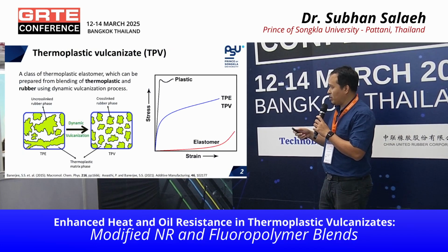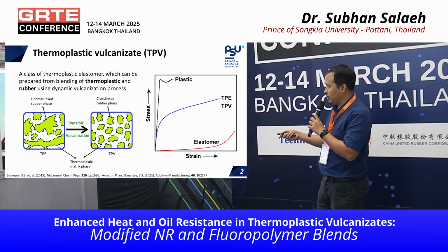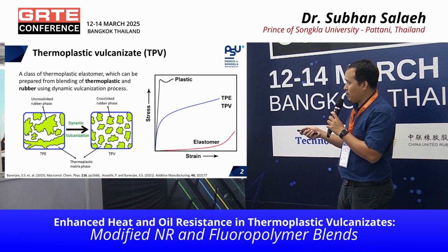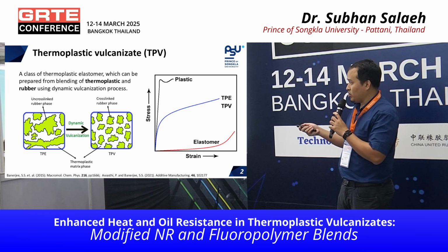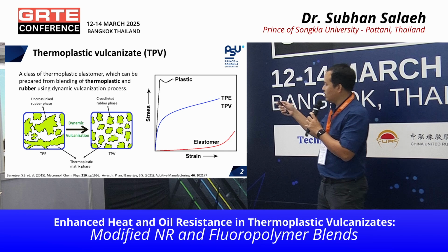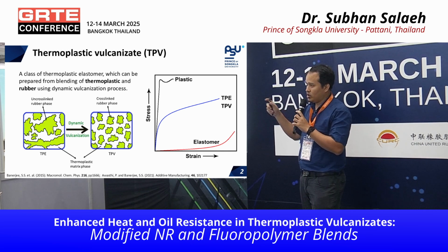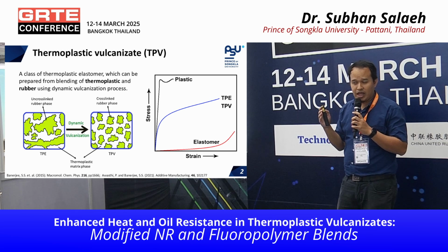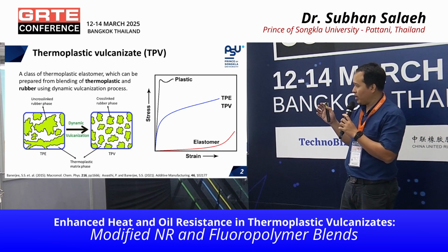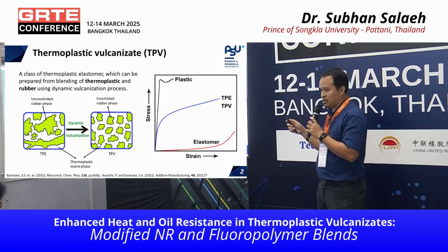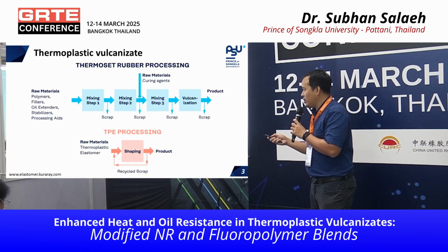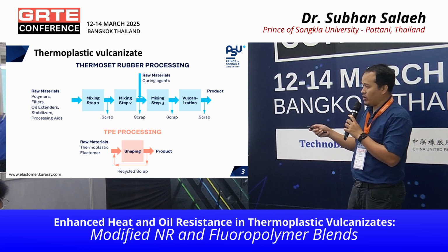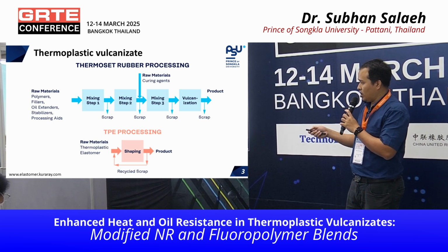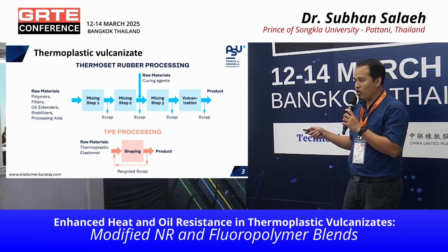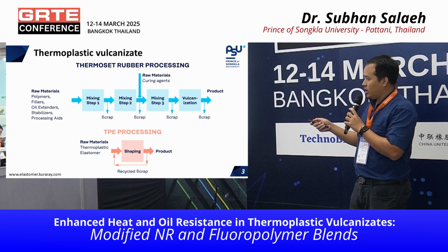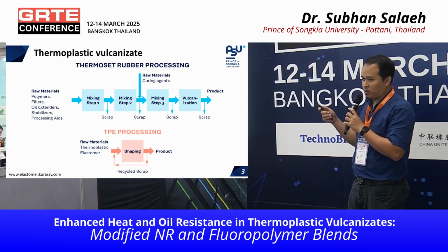After dynamic vulcanization, we can see that the crosslinked rubber is dispersed in the thermoplastic matrix. Due to this structure, we obtain a TPE or TPV material which behaves like a rubber-like material. It has high elongation at break, low modulus, and good elasticity. Another advantage, compared with conventional rubber, is that this material consumes lower energy.